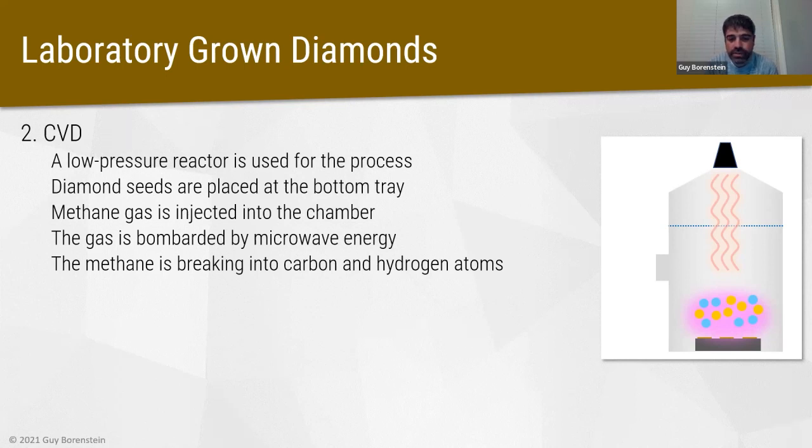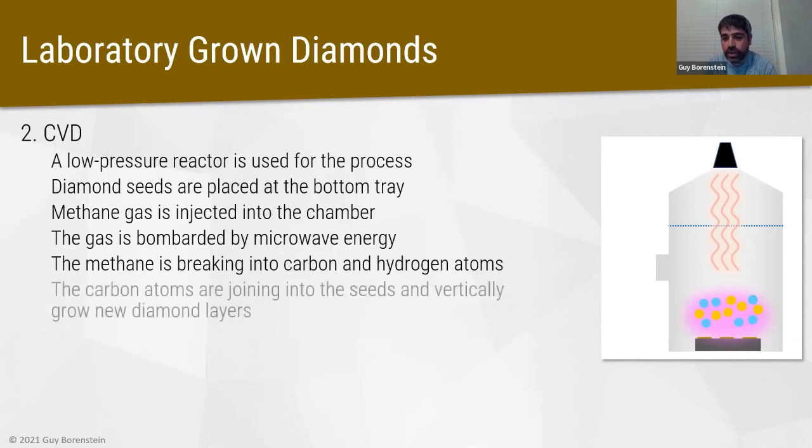So every graphite connection will be destroyed and the atoms will go back into the cloud. On the other hand, every diamond connection will be strong enough to hold and will allow us to start to grow these diamonds. And these diamonds will be grown vertically. You see that the crystals are being grown just in one direction, upward.